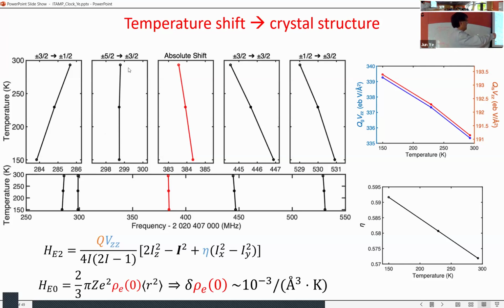But what's really interesting is that, because you have splittings, you can actually drive, suppose NMR or NQR worked, you can build co-magnetometers or co-electrical measurements to measure the crystal parameters in situ. At the same time, you pick the best transition between the ground state and excited state, so you have minimum sensitivity to the external parameter, but the external parameter itself can be measured independently.